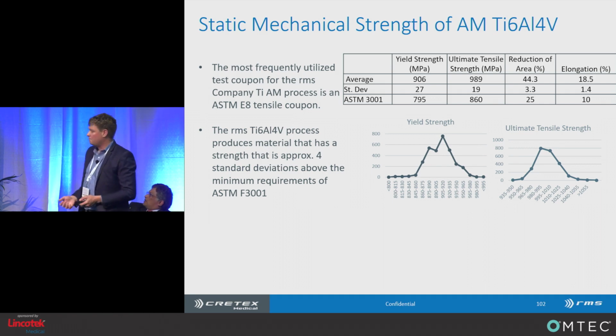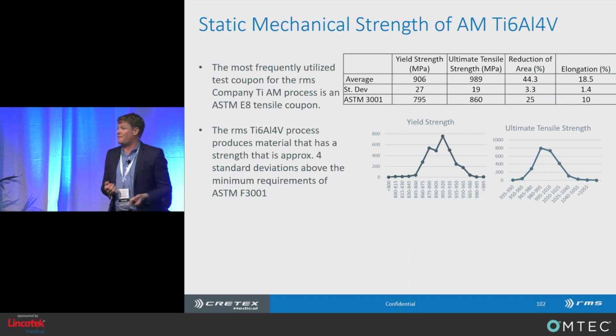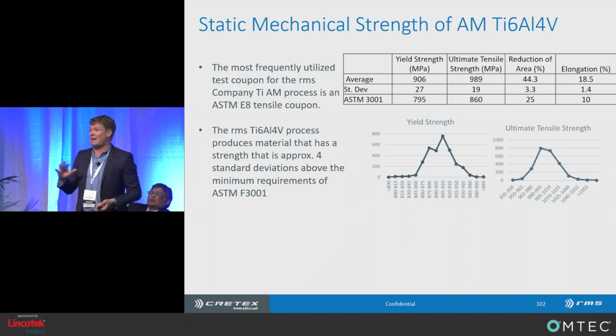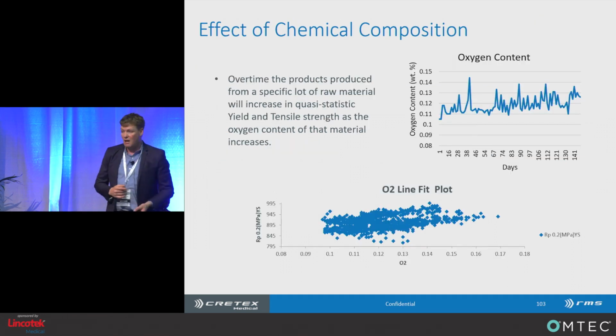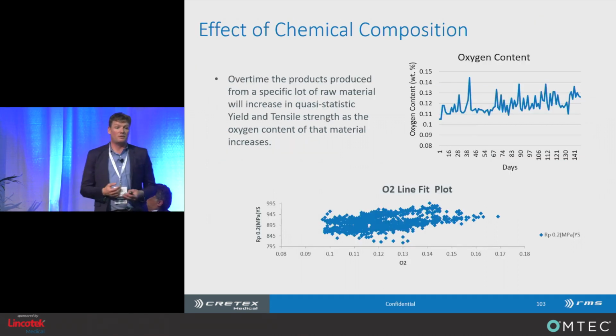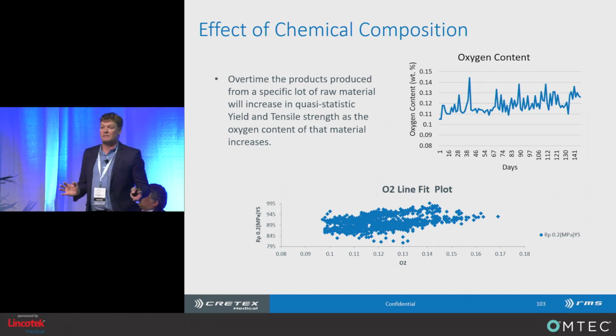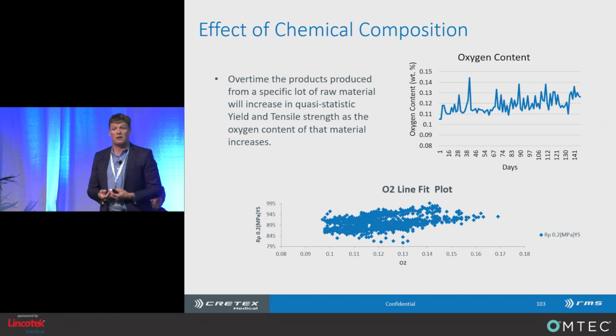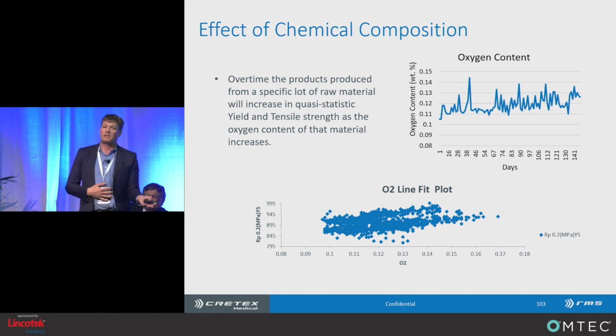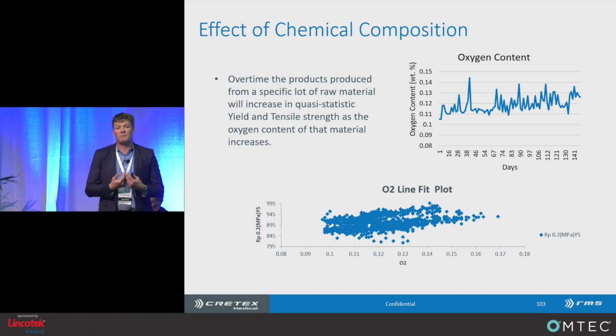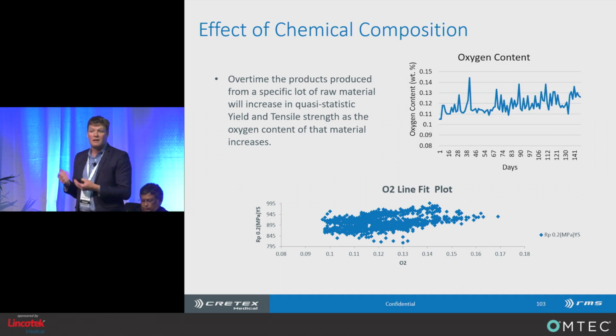So additively manufactured Ti-6.4 can be quite strong. Let's talk about ways that we can actually influence what those static strengths are, right? One of the best ways to manipulate the strength of additively manufactured Ti-6.4 is by changing its oxygen content, right? So lower oxygen content typically results in lower yield and tensile strengths, and as that increases, generally the yield and tensile strengths increase.